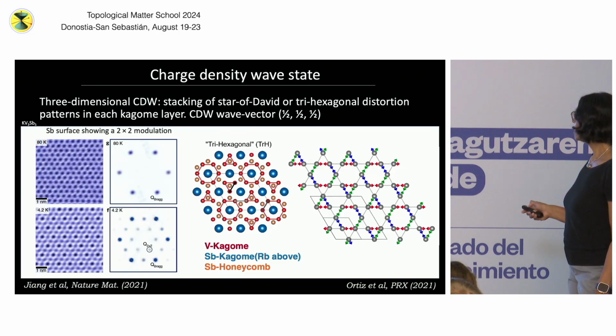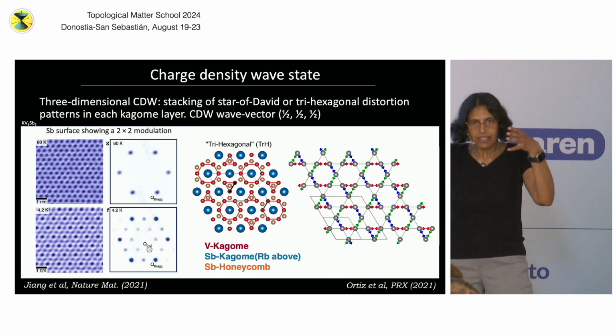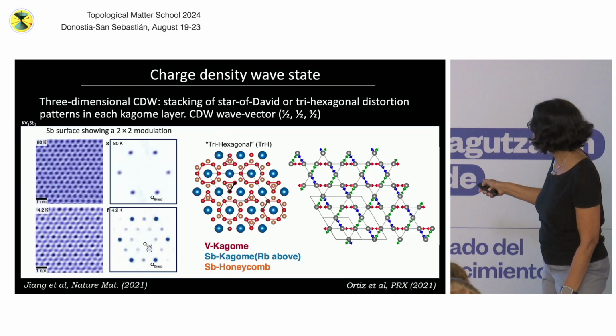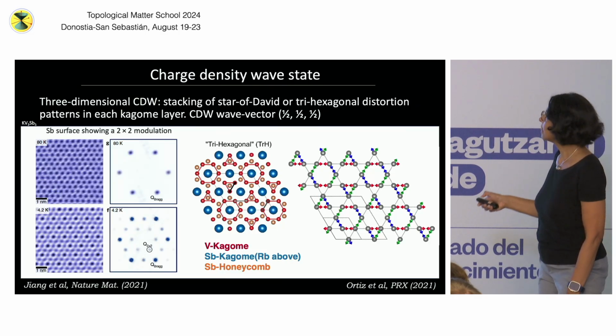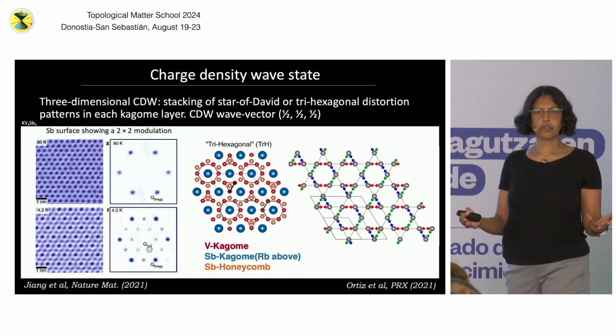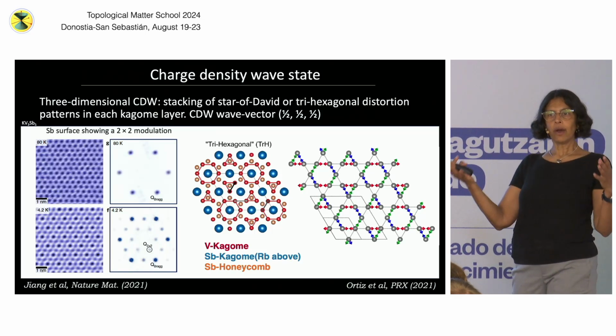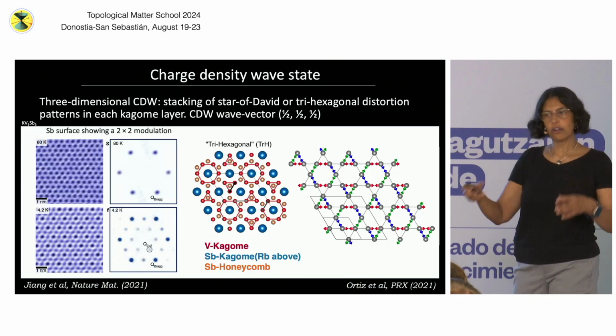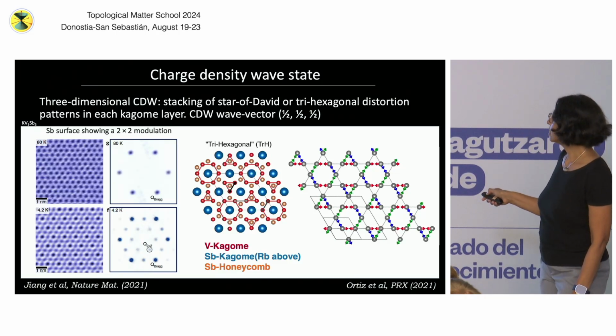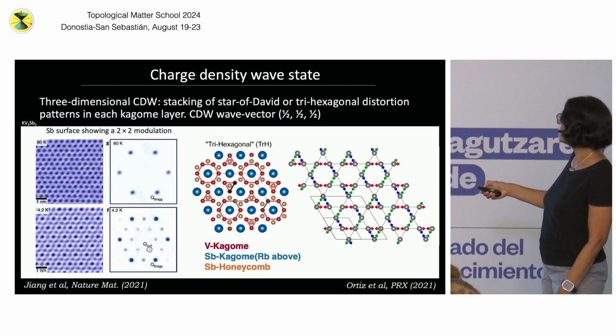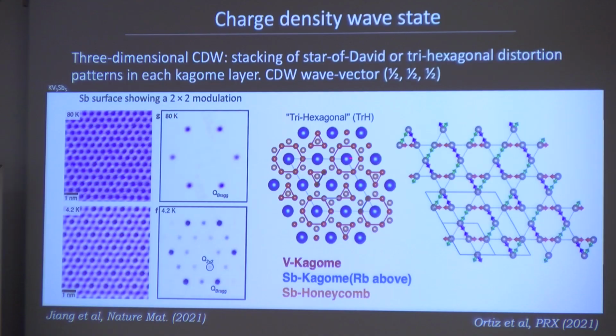So in real space, what happens is you get this sort of trihexagonal charge density wave where all of these atoms shrink a little bit, just a tiny bit, okay? So this ring of atoms just shrinks towards the center, and then this ring of atoms shrinks a little bit towards the center, right? CDW is associated with electron-phonon coupling. Whenever you have a charge density wave, you also have lattice distortion. This is the lattice distortion that you see in the system. All of these atoms basically go a little bit towards the center, so then you have bright, dark, bright, dark. That's what the CDW is. Okay.